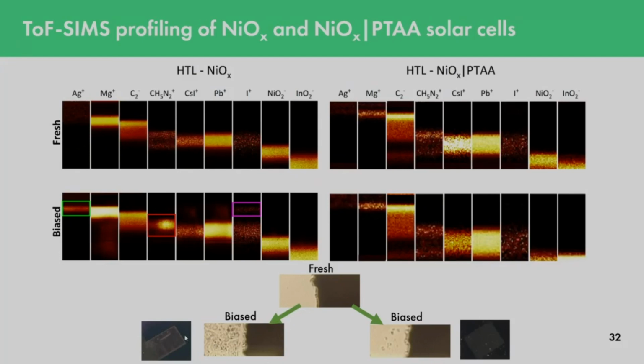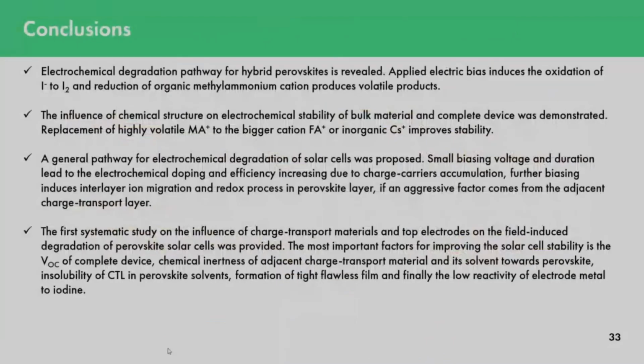And if we look at the nickel oxide PTA device, we first of all observe no such drastic changes as for pure nickel oxide material, only slight intercalation of various ions into neighboring layers. And if we look at the electrode, the changes are also not so drastic. And if we look at the photos of the backside of the electrode for nickel oxide, you can see, especially at the edges of the electrode, that the corrosion starts significantly. And after some time, this corrosion will also spread all over the device. So it usually starts from the edges and then spreads everywhere.